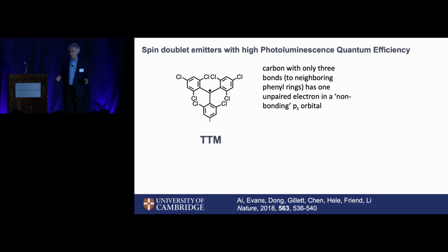They're enormously interesting. They're very serious candidates for secondary, rechargeable batteries, because redox involving radicals can happen very efficiently and surprisingly stably. And back to the stability, the electronic stability just depends on where the energy levels are for oxidation and reduction. If they're at the same sorts of energies as we are quite happy with for the molecules in standard OLED displays, we don't have a chemical instability associated with them being very hard to access electronically. TTM does that, but it's dark.